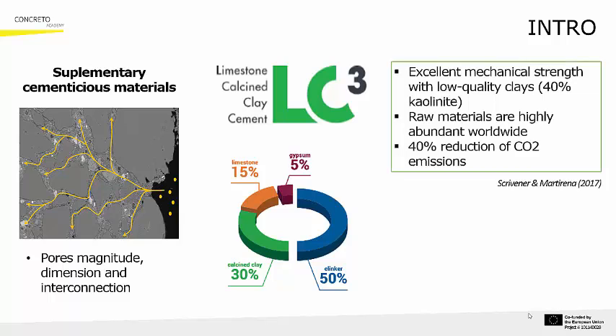Research has already demonstrated that LC3, made with only 50% clinker and with a calcined clay to limestone ratio of 2:1, even using low-grade kaolinitic clay, can produce concrete with mechanical strength at 28 days comparable to conventional concrete. This is achieved while obtaining a 40% reduction in CO2 emissions and the use of raw materials that are abundant worldwide.